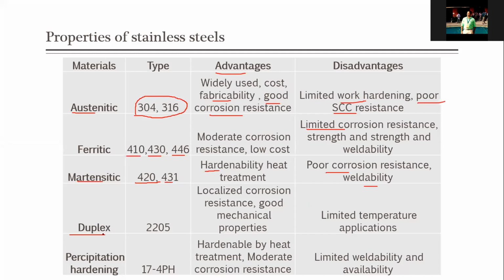And coming to the newly developed duplex alloy steel, it has a very good localized corrosion resistance, that is, resistance to pitting and crevice corrosion is very good in duplex stainless steels, and it has good mechanical properties also. When compared to austenitic stainless steels, the mechanical property of duplex stainless steels is very good, and the corrosion resistance also is very good. The only limitation of this duplex stainless steel is its limited operating service temperature.